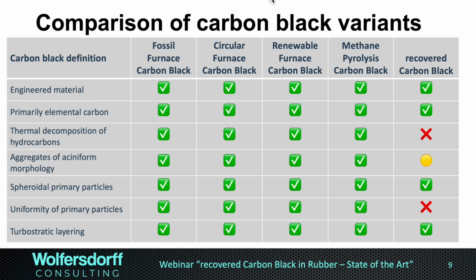Very often we have, in fact, the opposite of it. We have like a sponge-like microscopic picture, which is due to the carbonaceous residues surrounding all of the recovered carbon black. And then we have the gas exiting in the pyrolysis, this kind of sludge, and it solidifies, and that is our recovered carbon black. So we have the inverse of grape-like, we have like a sponge-like very often. Plus uniformity of primary particles. We don't have that because recovered carbon black, as we will see in a moment, is a mixture of carbon blacks plus some other material.